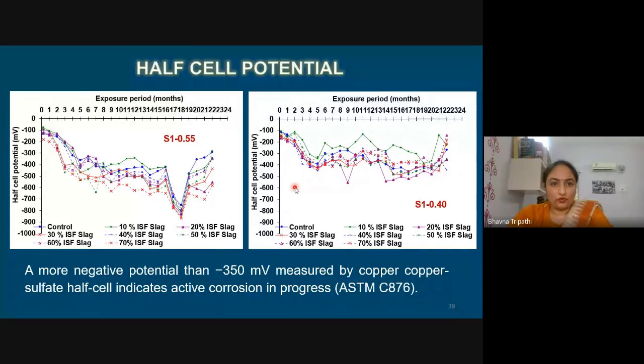Another test was half cell potential on the same specimen. This was recorded by disconnecting the connection of anode and cathode and taking the potential difference with the help of a copper sulfate half cell. An anode potential less than minus 350 millivolts was considered to be an indication of active corrosion in progress. So we can see that in this particular mix, there is a sudden dip at the 18th month.